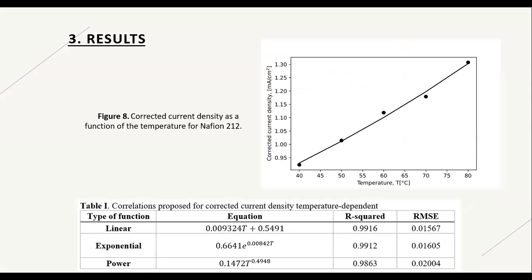The data trends shown in figure 8 indicate that the temperature proportionally affects the hydrogen crossover. This phenomenon can be explained by the gas permeability coefficient, which depends on the temperature to which the gas is subjected. The diffusion coefficient is also affected by the particles movement, and a higher temperature implies that the particles have higher energy, so they collide more quickly with the membrane surface, causing hydrogen diffusion to increase. This implies that the degradation of the proton exchange membrane is accelerated when working at a high temperature, since the hydrogen permeability would increase each time, which can cause the formation of hydrogen peroxide during cell operation.